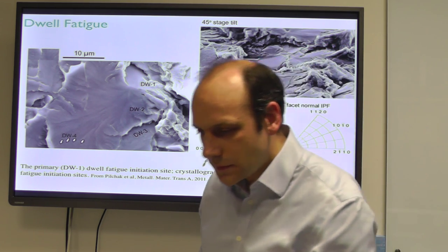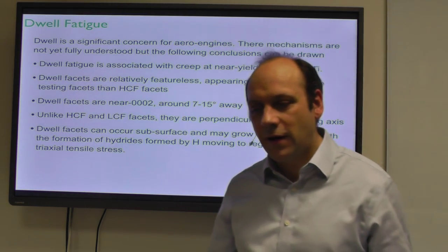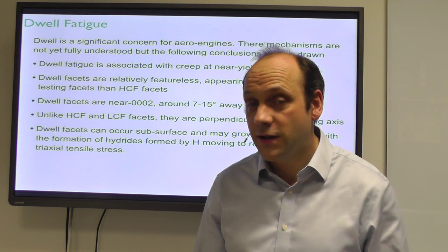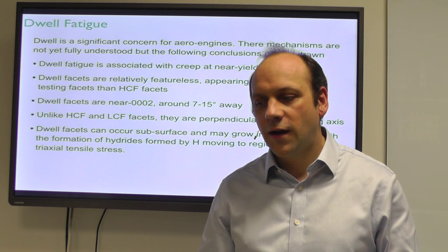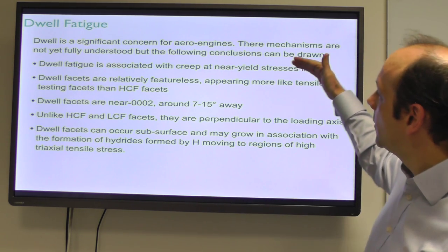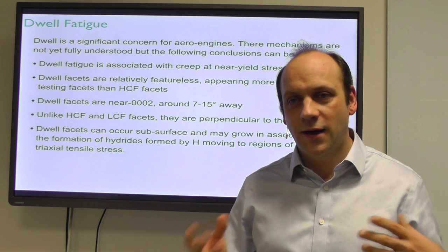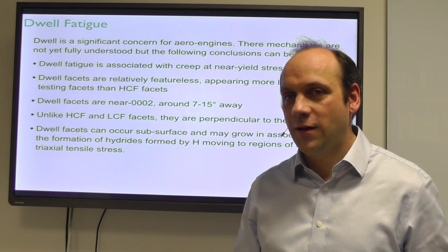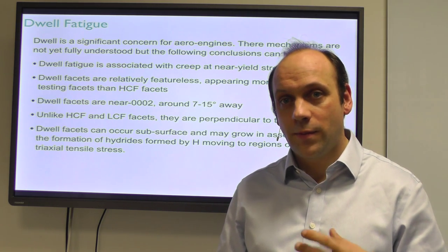deforming. So just to make some comments on dwell, it's a significant concern for aero engines. Back in the early 70s, Rolls-Royce had some problems with dwell fatigue, actually. The mechanisms aren't yet fully understood, but we can say the following things. Dwell's associated with creep at near yield stresses in titanium. Titanium, when you take it up to nearly the yield stress and hold it, tends to creep, and it seems to be associated with that plastic relaxation.